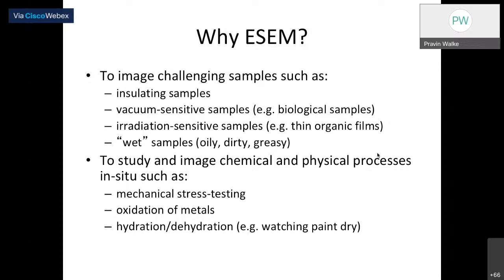Further, the oxidation of metals. If you have less vacuum, then there is a possibility of forming oxidation on the surface, and how that in situ oxidation happens can be seen by using the ESEM. Further, hydration and dehydration, for example, watching how your paint is getting dry. Once you put the paint on the sample stage and put it inside the SEM, you can see how that paint gets dry. That kind of study can be done using the ESEM.